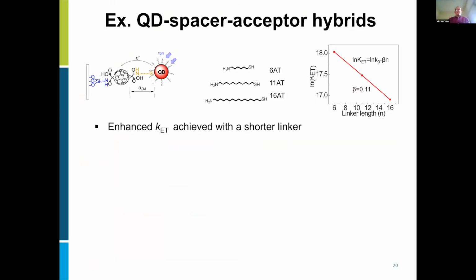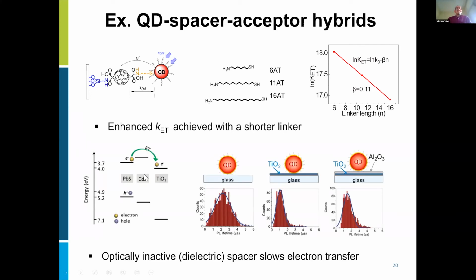Some other examples here, not necessarily band gap engineering, but using donor-acceptor distances: a quantum dot connected to the carbon-60 that I introduced on the previous slides. We use varying alkane thiol linkers, where the thiol connects to the quantum dot, and the other end connects to the carbon-60. When we compute the rate out of the lifetimes, we see an exponential dependency, which tells us we can control the rate through these linkers. And at shorter linkers, obviously, we obtain stronger electron transfer.